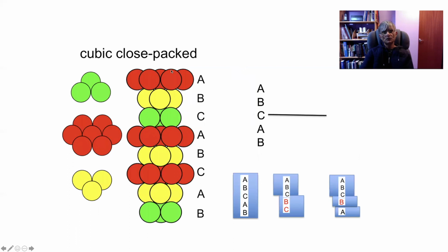So we know that in the face-centered cubic, or cubic close-packed system, we have these close-packed layers of {111} planes, which are in ABC, ABC, ABC stacking, repeat of three. So let's begin with this stacking sequence, ABC, AB. And we are going to twin about this plane C, and therefore that C plane is not at all altered. Now the notation ABC